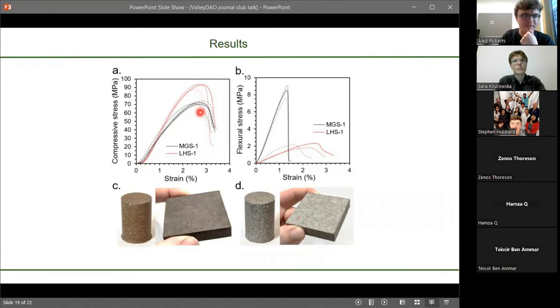It suggested that there weren't any nuisance variables affecting the results, and that's the good thing about doing design experiments. We screened out so many factors that it would tell us if there's something important affecting the results, so you can rule out nuisance variables, which if you don't do early on, you can get annoying variation in your results and you don't really know what's going on. And when we translated to lunar highland simulants, so moon dust essentially, it was even stronger. We got up to over 90 megapascals in compression.